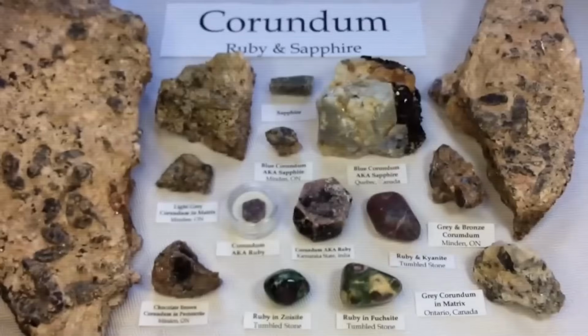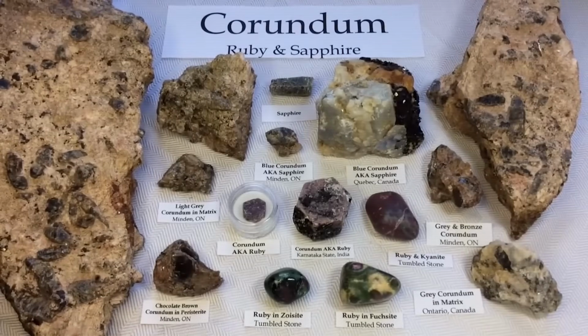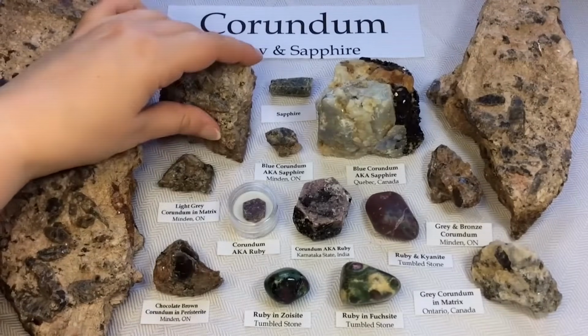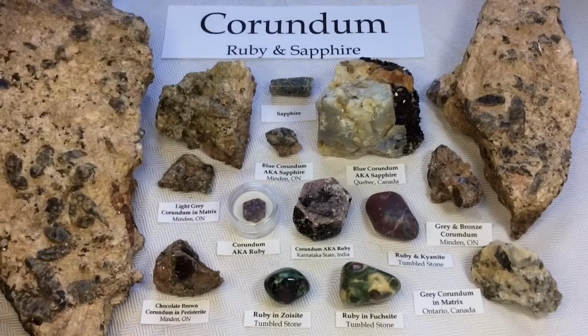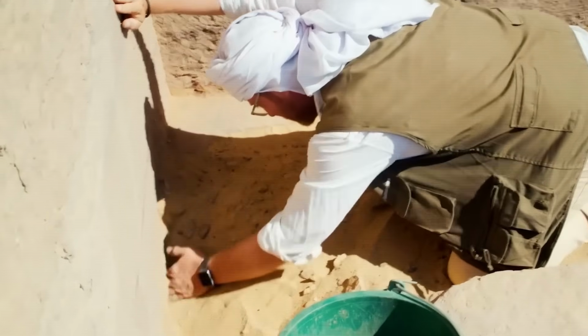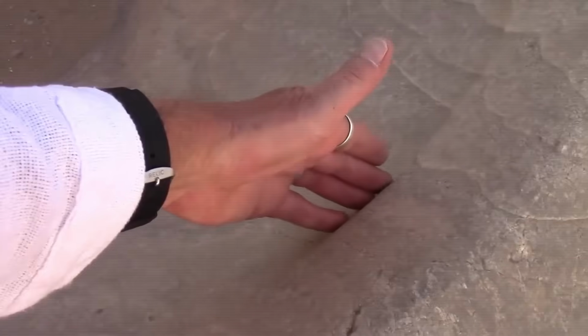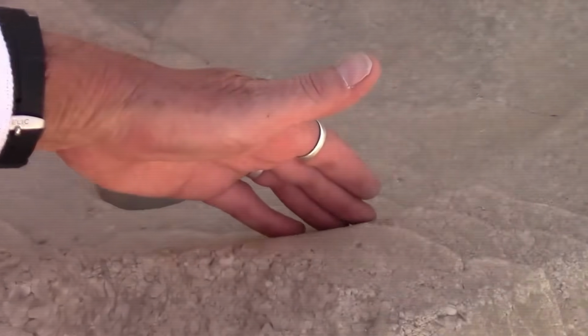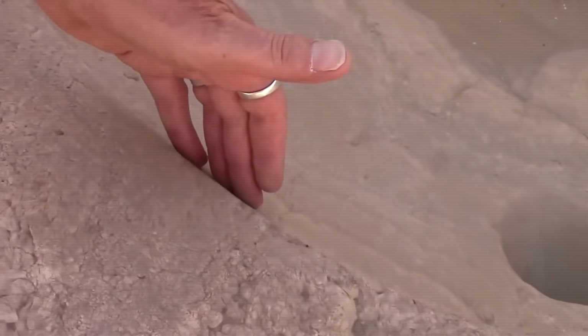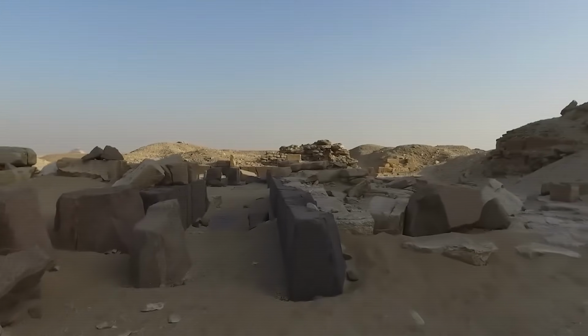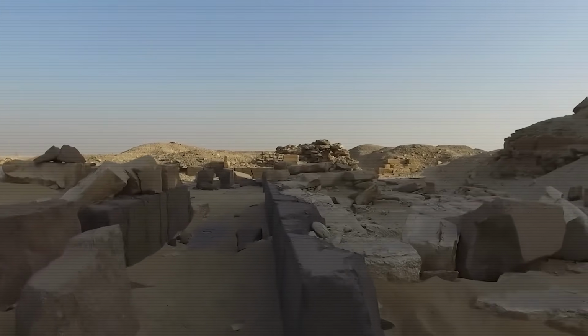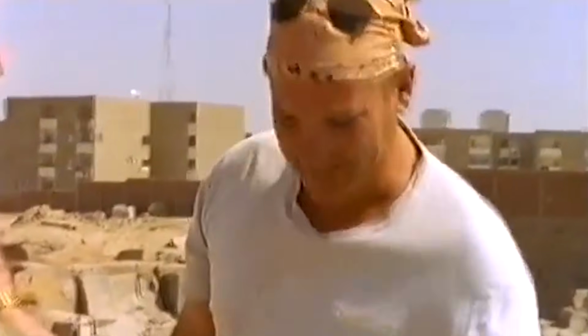Copper with sand, roughly 0.5 millimeter of cutting depth per hour, painfully slow, heavy copper degradation, rough, uneven surfaces that matched nothing in the ancient record. Copper with quartz powder, approximately 0.8 millimeters per hour, marginally better, still nowhere near the performance required to explain ancient output. There's no, without a steady stream of water, you're not getting new material in there to do the cutting action.